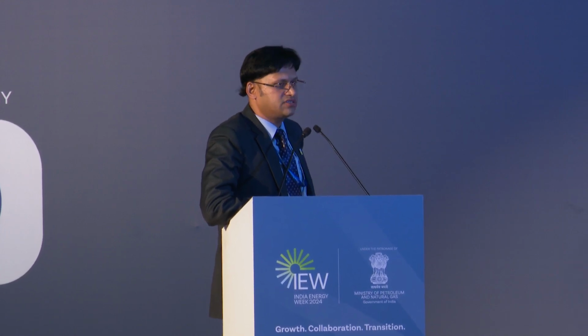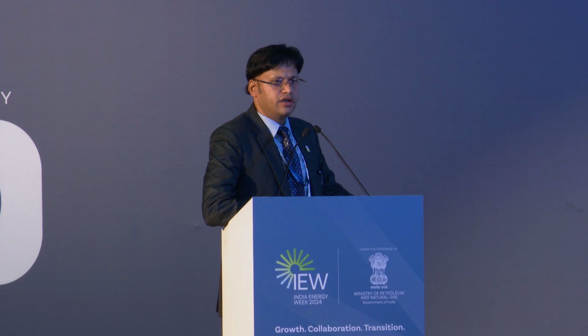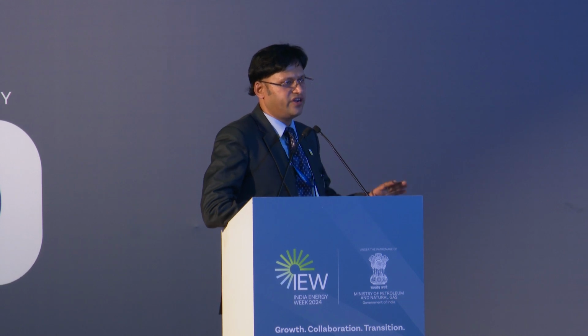When we searched what has happened with the globally demonstrated hydrogen compression systems, we found very latest demonstrations happened in the past 3-4 years, globally in Switzerland, Africa. And you see these metal hydride compressors are used for low hydrogen flow rates, but they have gone to 250 bar as well, and the operating temperature is 150 degrees centigrade. Now in places like refineries and industries, there is process heat which is of 150 degrees centigrade. And people have used this system for hydrogen refueling stations, fueling the forklifts. So from this we got a clue that if the globe is working on MH systems, Indian companies can also explore the potential of this.